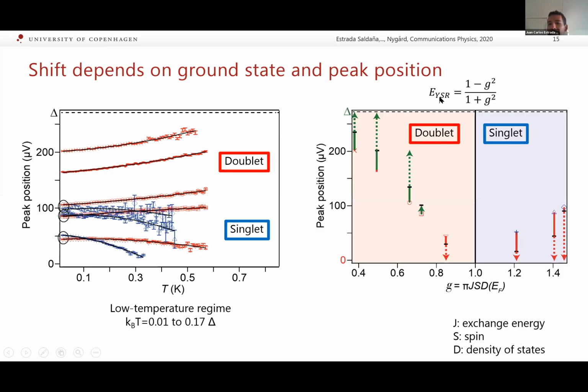We can parameterize this behavior by using this G parameter, which equates the position of the YSR peak to this G parameter. And this G parameter is nothing more than the exchange energy up to a constant factor. So we plot this peak position versus exchange energy up to a constant factor. And here we have, in green, peaks which shift towards delta, and in red, peaks which shift towards zero. And we can see, again, the same thing as here: before the doublet to singlet ground state transition, the direction of the shifts changes.